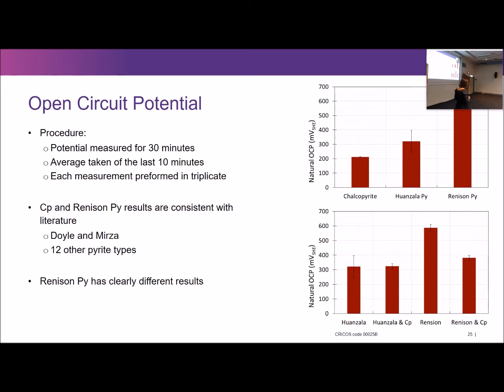So, first thing that happened is I measured the open circuit potential, which gives me an indication of the rest potential and the baseline electrochemical activity of these minerals, the chalcopyrite and the two pyrites. So I started off with just measuring the potential at rest for 30 minutes. I took an average over the last 10 minutes of the test just to give the system time to equilibrate, and repeated everything in triplicate. I did the measurements on individual minerals as well as in mixed galvanic pairs, where I connected two minerals together and allowed them to interact.